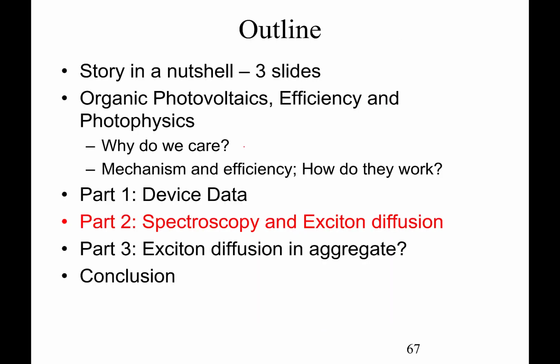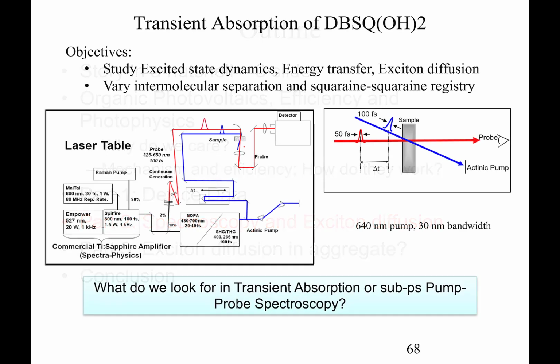So the next part here I'm going to talk about is the spectroscopy and exciton diffusion. And so what we've done is we've worked with Professor Dave McCamant at the University of Rochester, and this is a transient absorption system over there, sub-picosecond transient absorption system. We use a Ti:sapphire laser, and we look at the excited state dynamics, energy transfer, and exciton diffusion. What we do is we change the intermolecular separation, and we're actually going to dope some of these squaraines into polymethyl methacrylate as a solid solution. And we can also do some work where we anneal the samples even in polymethyl methacrylate, and at some point improve the squaraine registry.